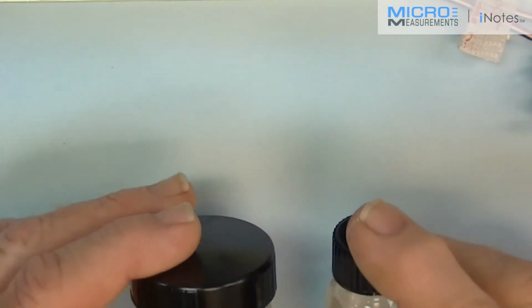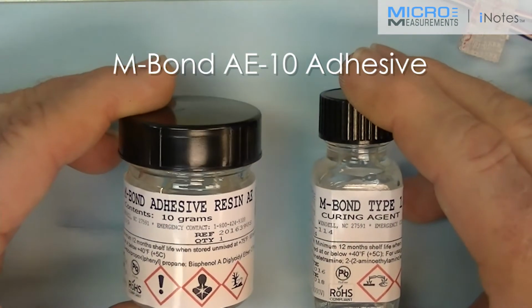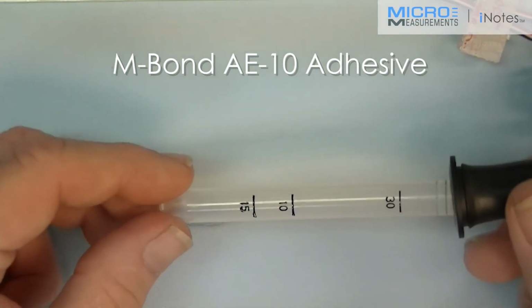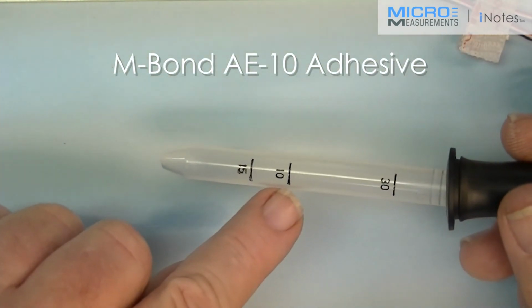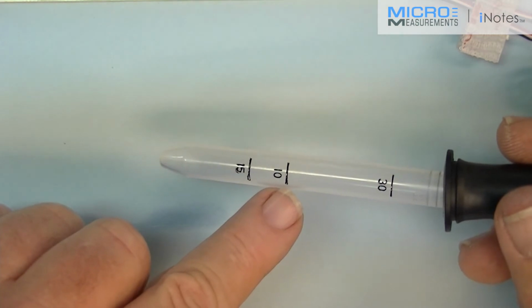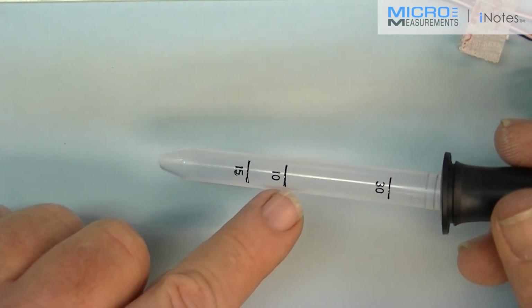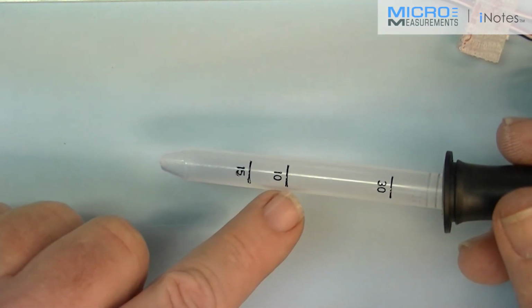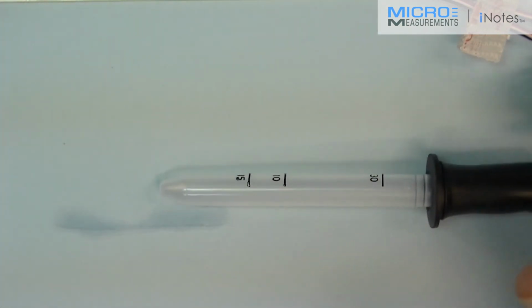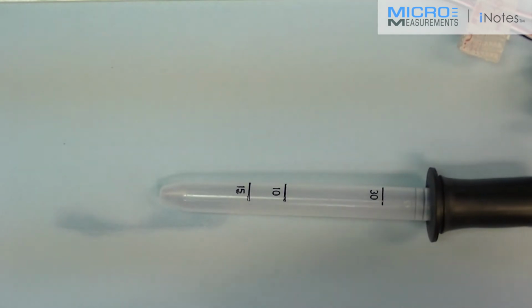The next step will be to mix the AE10 adhesive system and curing agent. We will carefully measure out and dispense the curing agent to the mark 10 for type 10 curing agent, remembering that the meniscus, the lower line, is the one that we want to use to measure that. I cannot show you pulling this up in the video because I can't do it vertically.